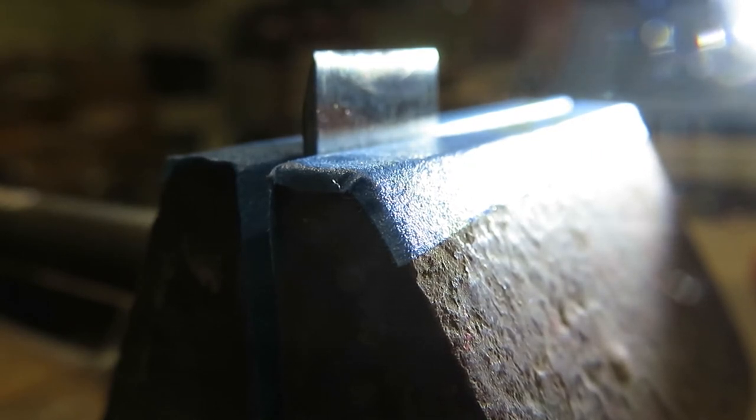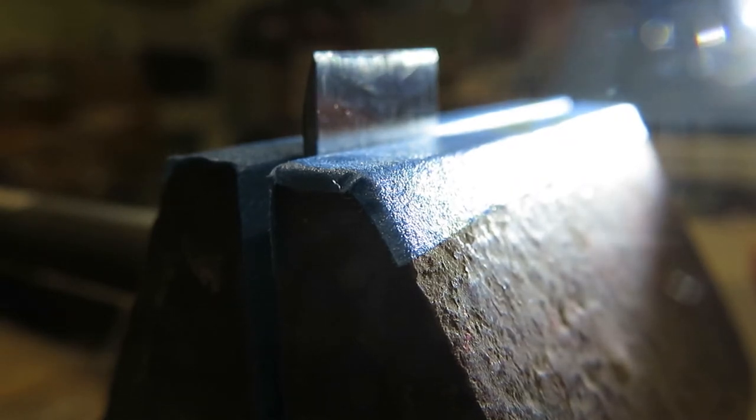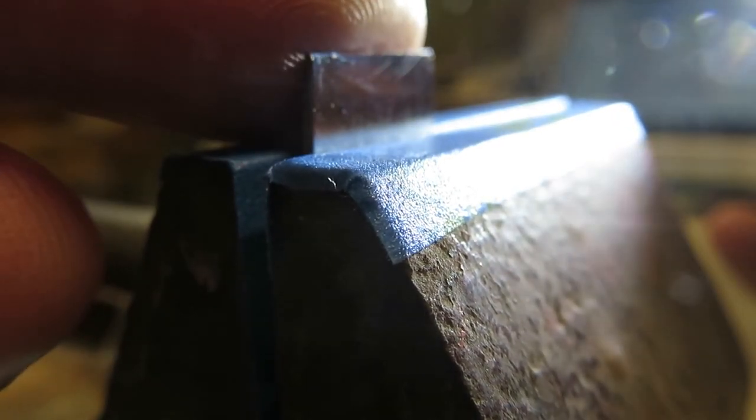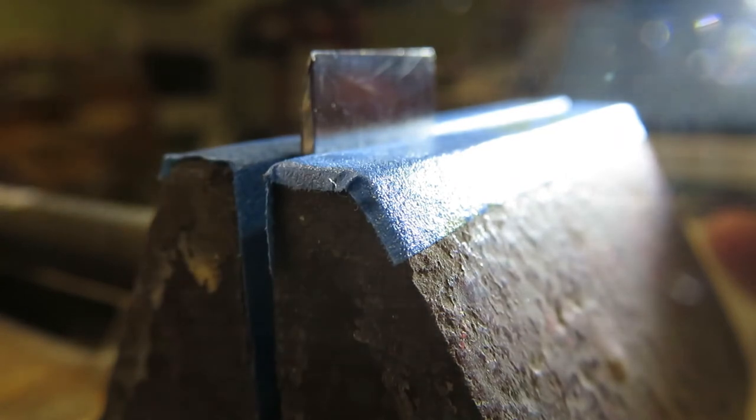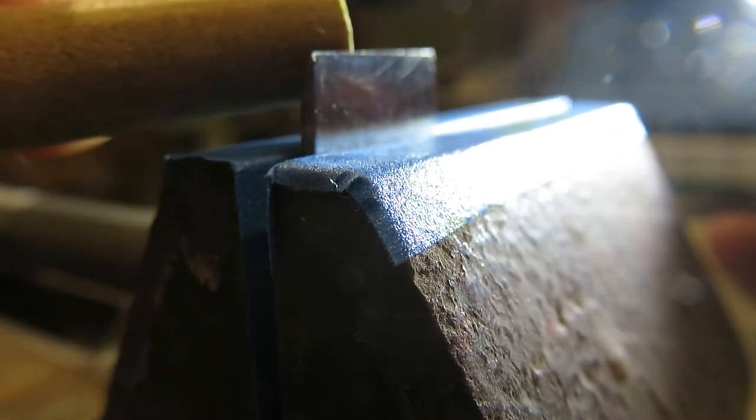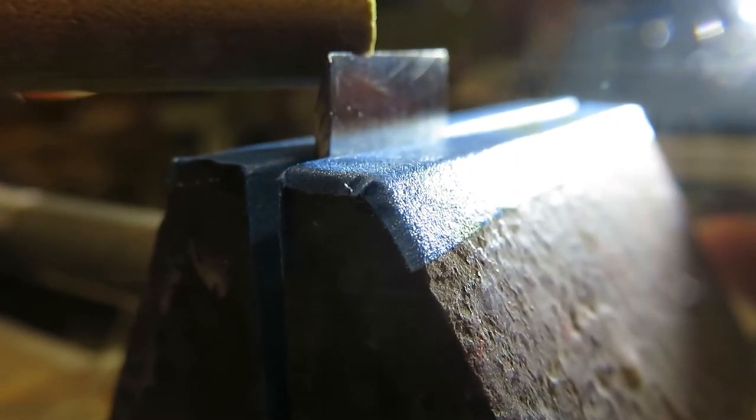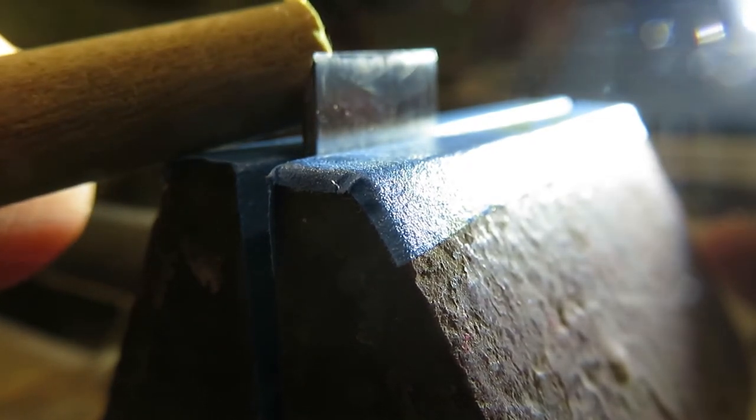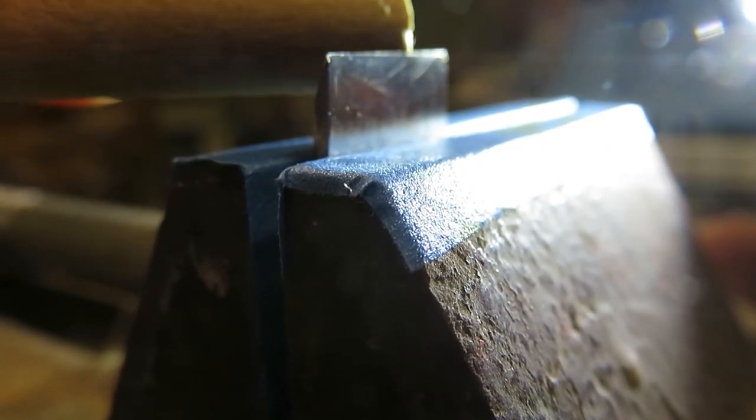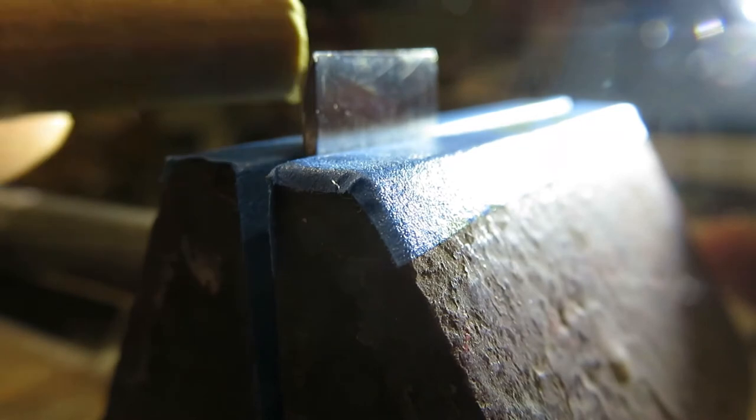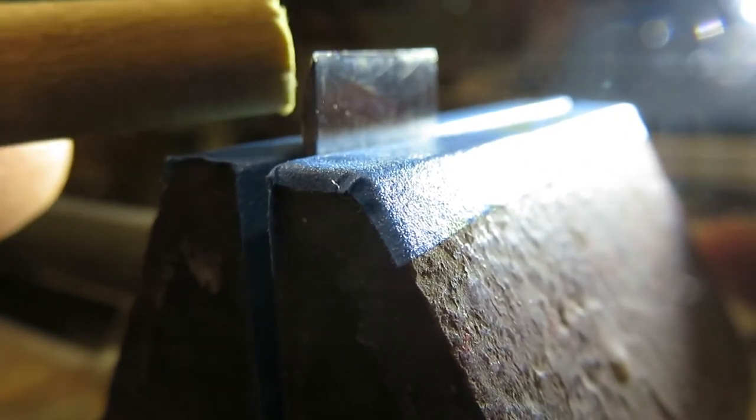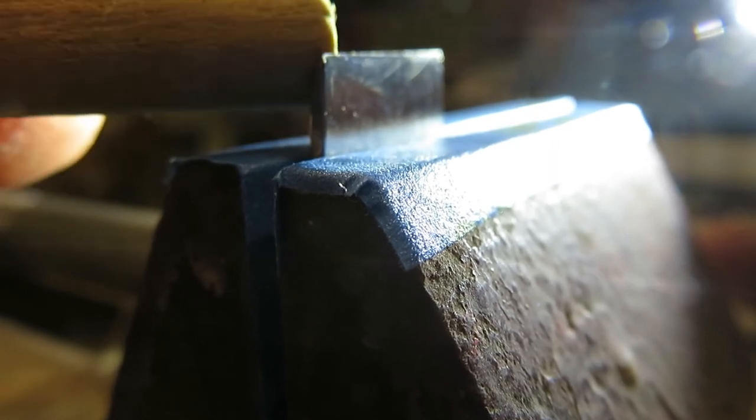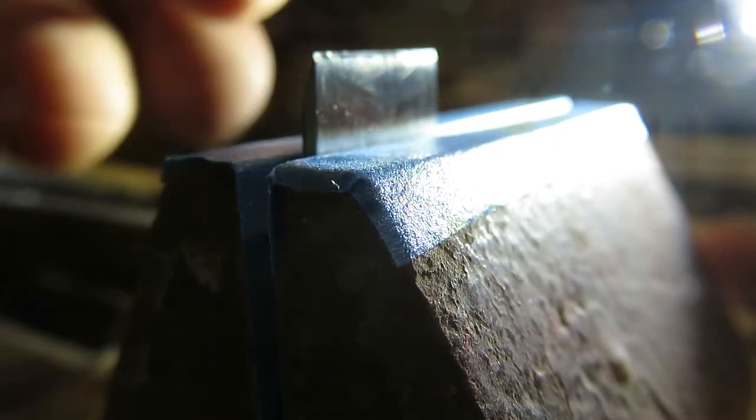I'm going to show you a cutthroat head that I took a hog with. I didn't resharpen it purposely because I wanted to show you this. Now that one's sharpened at 24 degrees. This is only 20 degrees, and there are makers out there making 20 degree single bevels now, and it will give you more rotation, no doubt. But at what cost? When you can push that edge over and distort it with something as soft as a wooden dowel and not a lot of force, when this hits massive bone you're going to see edge distortion, edge deformation, edge damage. So I contend that 20 degrees is too shallow of an edge to try to make a broadhead blade.